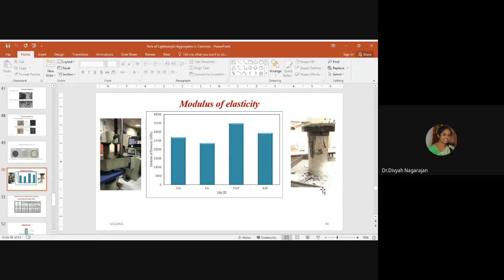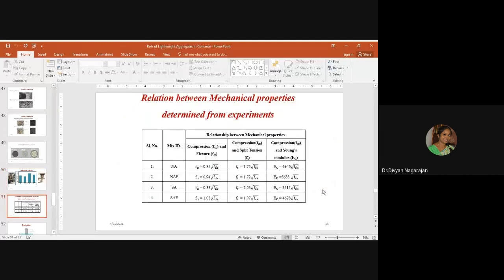Yes, when 100% replacement of the coarse aggregate is done, there will be lower peak stress. That is, determination of the elastic modulus of manufactured aggregates is highly impractical because of the variation in the production process. The modulus of elasticity of the sintered fly ash aggregate concrete is comparatively lower when compared to the normal aggregate concrete, but addition of fiber increased the modulus of elasticity.